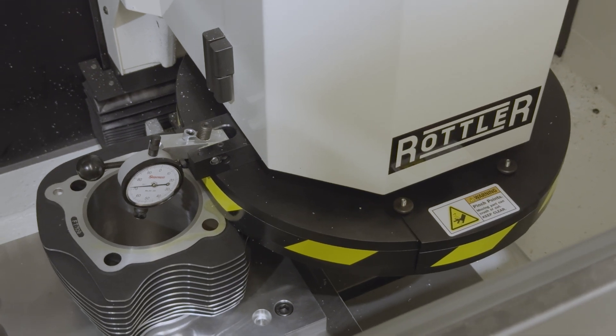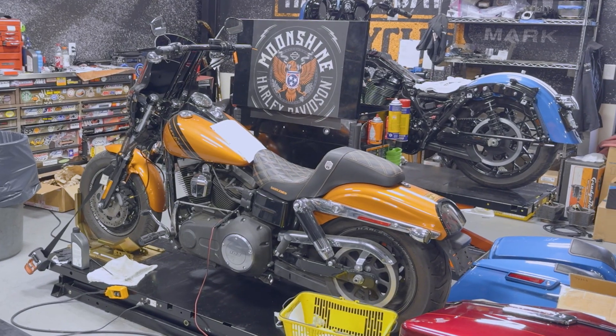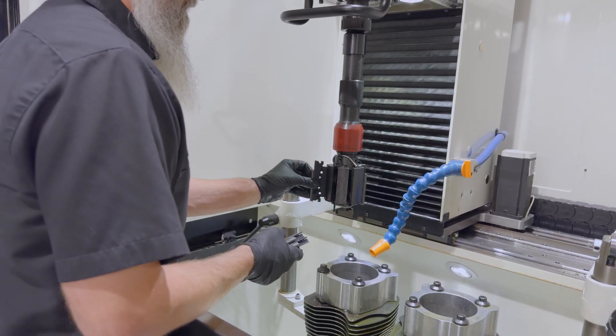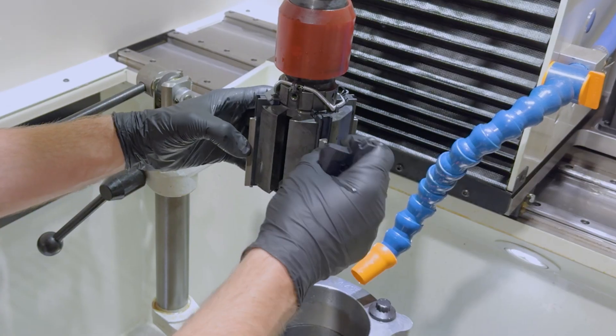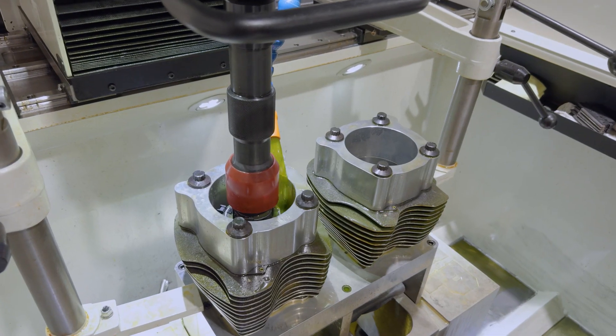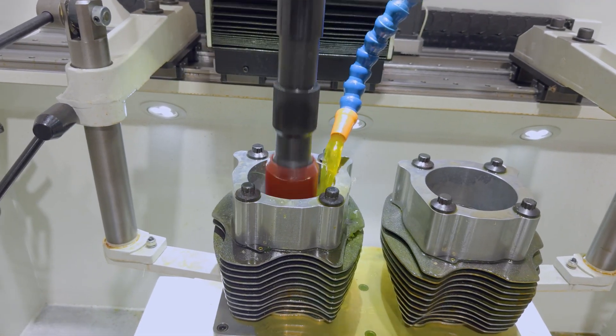It's a smaller servicer. Getting the machine set up with Rottler for our specifications and what we're doing was pretty memorable, because our stuff is a lot different than a normal small block or a big block. Our cylinder spigots are not supported by the engine case, so when you're honing them, they move. We're able to dial it in and buy the stones we need for the finishes on our cylinders. Because of the way they're supported inside the case of the engine of the Harleys, we're using really hard materials — tool steel and ductile iron — and it takes a more aggressive stone to get it there.